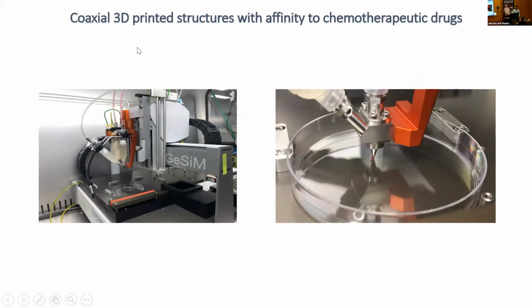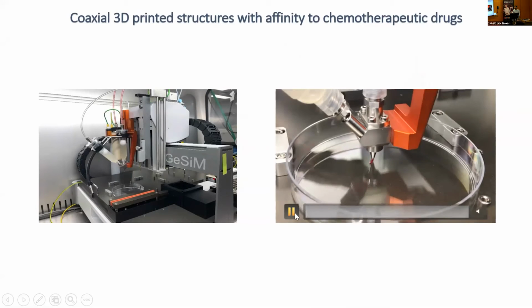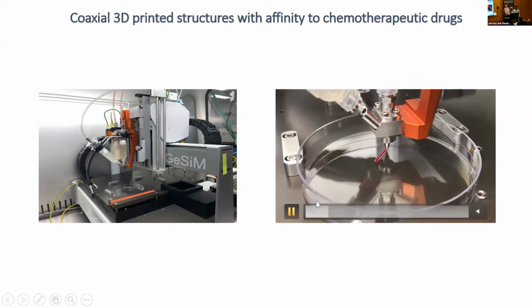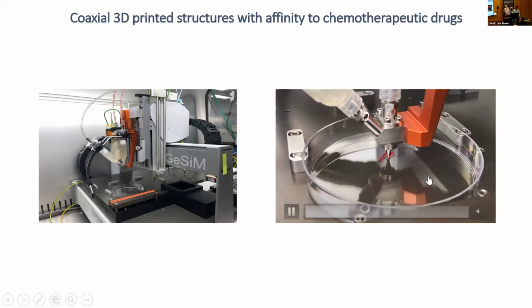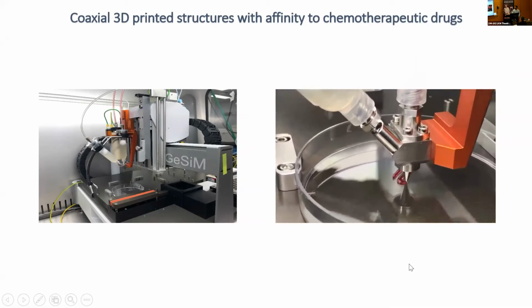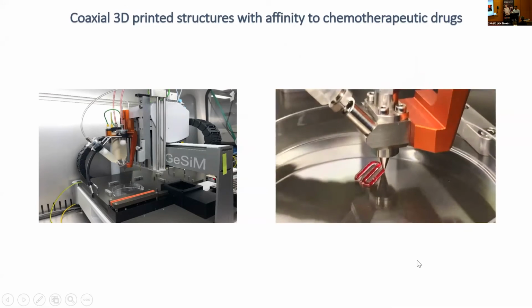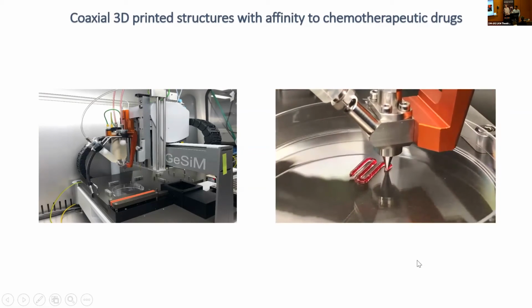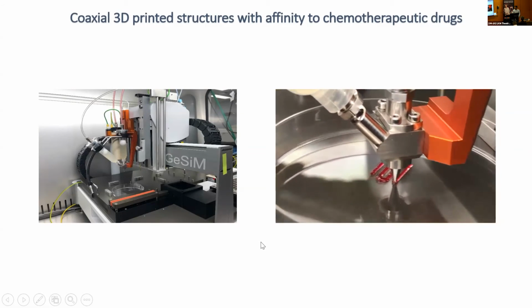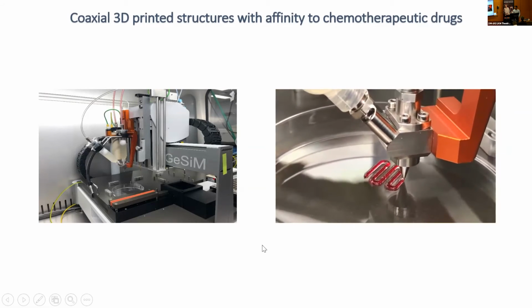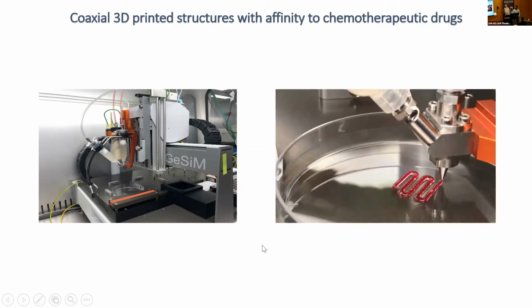And then lastly, because we didn't get good release results from those core shell fibers, especially in the case of gemcitabine, we decided to use the 3D printing facility that we have in ACES, especially the GeSiM printers. We printed the same formulation, but we made some minor adjustments to adjust the release rate. So we still went with the core shell structures that we designed with the same formulation.